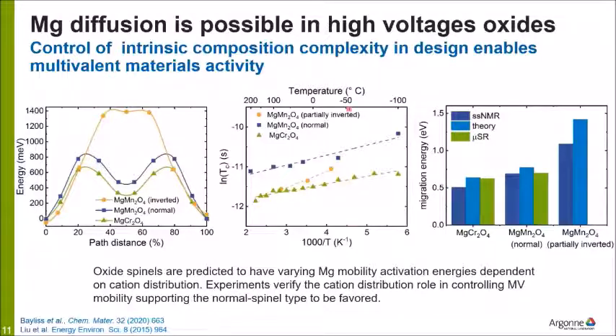We then experimentally, using NMR, this is compiled NMR data taken at variable temperatures, we were able to get activation barriers as a function of temperature, which correspond very nicely to the DFT calculations, as well as muon spin relaxation studies. And you can see here, on the far right is a comparison of the three techniques, and you can see the very close match between the three techniques. Finally, you can see that the chromite spinel of these three certainly has the lowest activation barrier. So we feel very confident that we've shown that indeed magnesium cations can diffuse at appreciable rates within the spinel oxide structure, and that it should not be the primary limiting mechanism for magnesium energy storage.